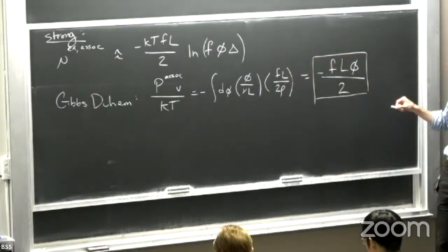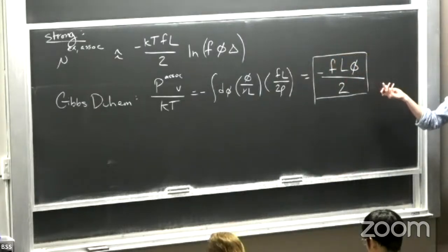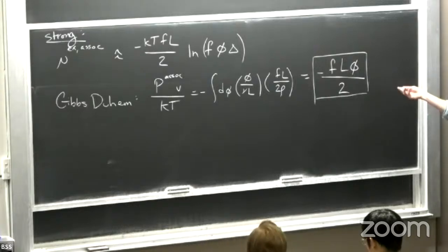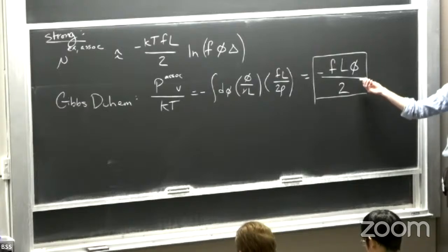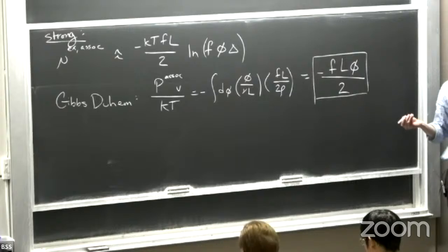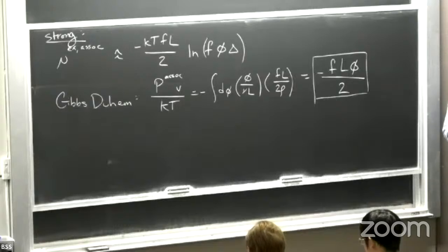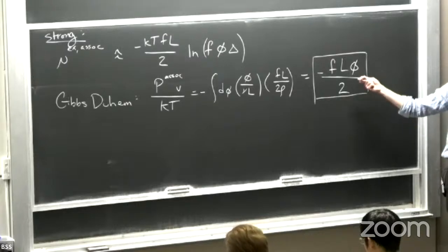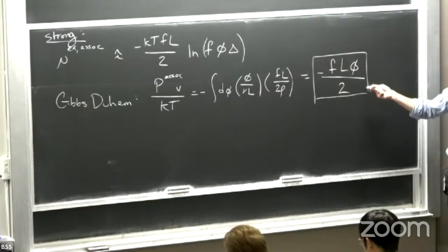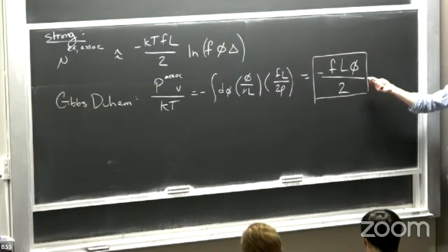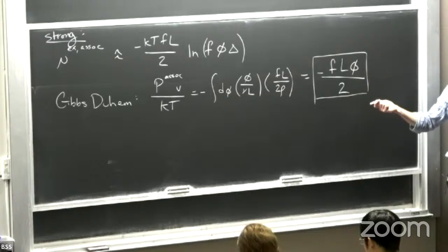Okay, so what's interesting about this? There's no delta, right? There's no association parameter anymore. We say that once the bonds become strong enough, your thermodynamics here doesn't depend on how strong those bonds are, because of this assumption that you have one-to-one binding, right? Everything that can be associated is associated, and this is going to change your phase diagram, right? In particular, it says that if you keep going to stronger and stronger bonds, you are not going to change the properties of your condensed phase, right?